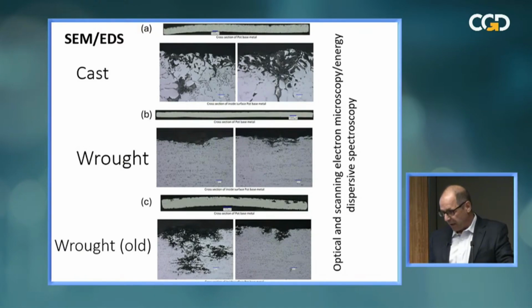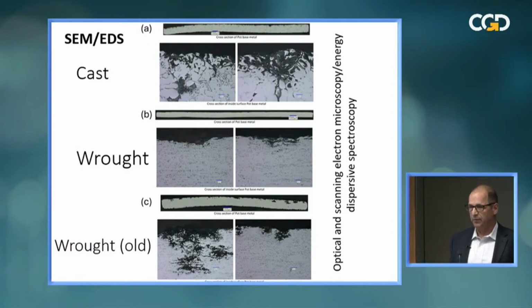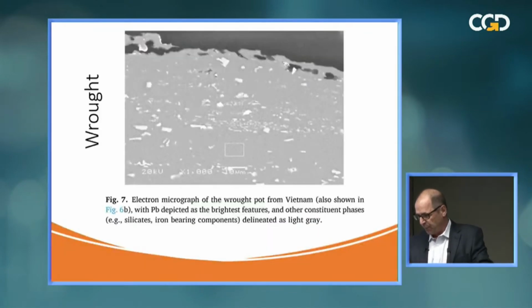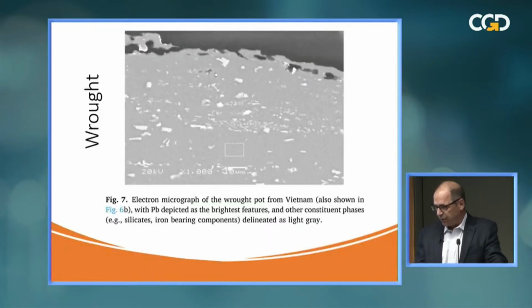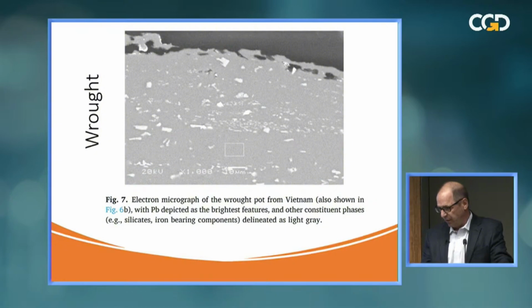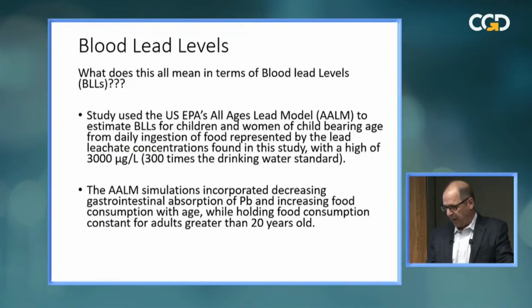Okay, the one on the bottom is an old pot where you can see that it's actually quite deep into the pot, and it does, again, follow preferential pathways. So there is a question of the accessibility of the lead to the leaching solution as the pots wear. Again, another close-up. This shows the lead inclusions at a much finer grain, also in a wrought pot.